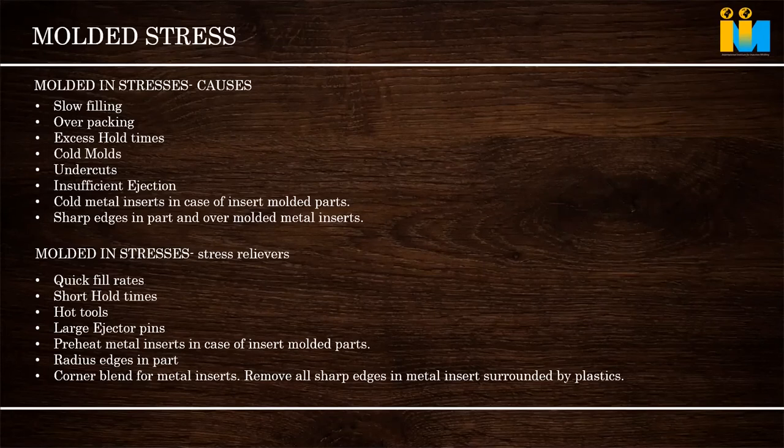Then some undercuts in the mold. We have seen plastic caps that just strip out of the mold, and we are not giving any mechanism. But not all materials are meant for just stripping out. Amorphous plastics are not meant to strip out. If it's a bigger undercut, we have to give some angular core or side core. But PP and such materials can easily be pushed out; it expands and comes out. Nylons also. So for undercuts in the mold, we must consider what raw material we have.